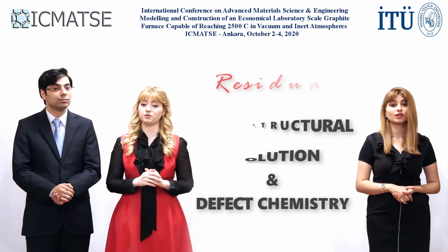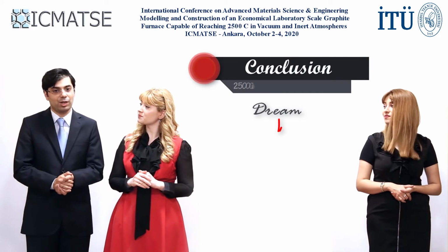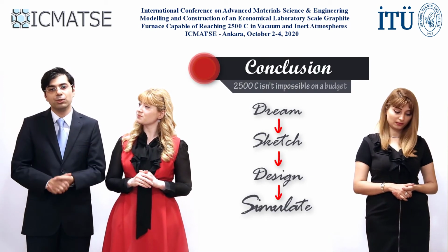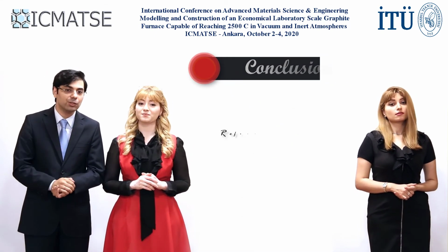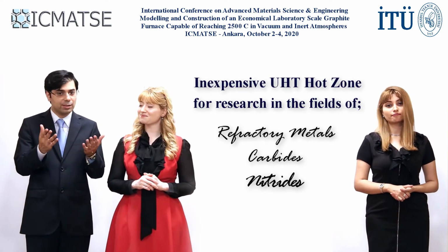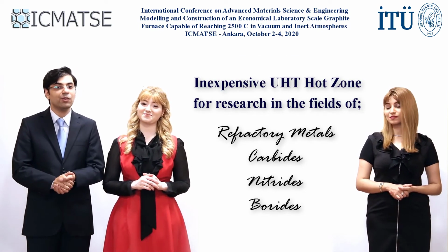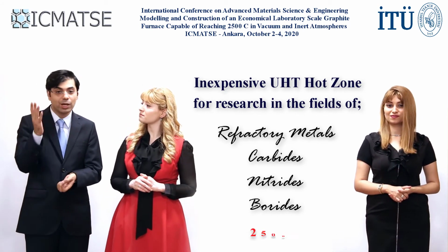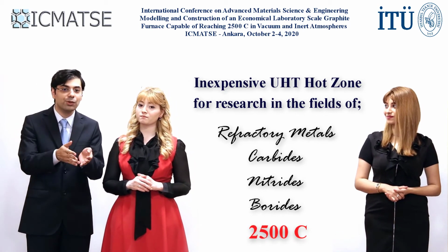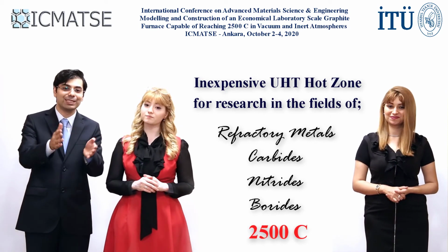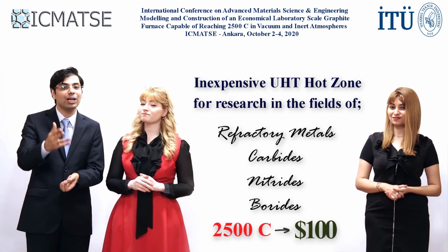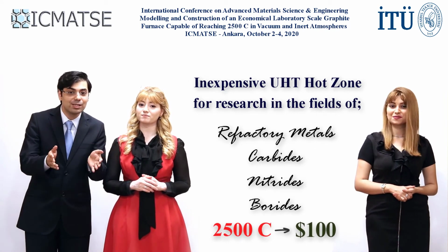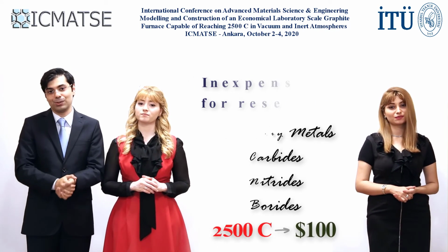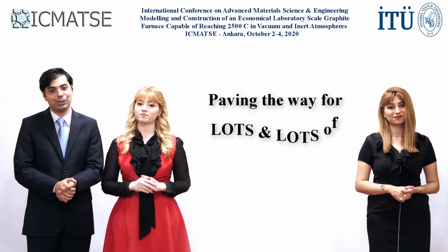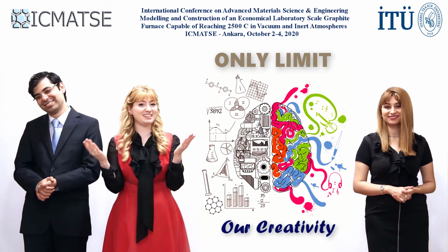So to conclude, every one of us researching in the field of ultra-high temperature materials, especially on refractory metals and their carbides, nitrides or borides, can build a graphite furnace capable of reaching temperatures up to 2,500 degrees Celsius by bringing together the equipment usually available in most labs and a hot zone of just $100 with the service life of several hundred hours, paving the way for lots and lots of high temperature experiments. With the only limit being our creativity.